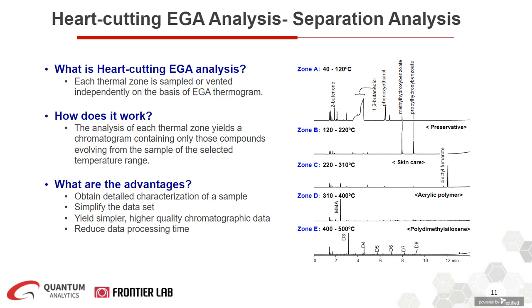So for the eyeliner example, using the heart-cutting mode of operation, we were able to obtain a separate GCMS chromatogram for each zone of the EGA. So in this case, 5 zones: A, B, C, D, and E. Zone A was performed from 40 to 120, then 120 to 220, all the way to zone E.